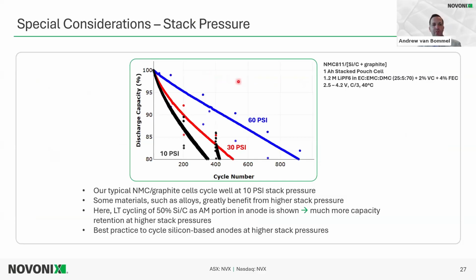So I'll go into a couple or three special considerations when looking at cell testing. One of them is stack pressure. So stack pressure, normally for our synthetic graphite cells, we use stack pressure of 10 psi, and that cycles well. We notice that for alloy cells with alloy anodes, including silicon type materials, they cycle better at a higher stack pressure. So this is showing that.